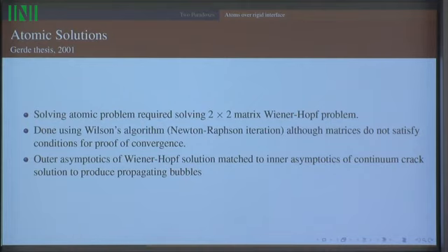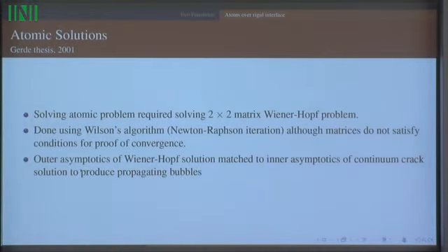So a little bit more on the way this had to run. If you believe in the existence of a continuum solution, then you can work out the asymptotics, which in terms of the power law, as you approach the tips. And I showed you that. It's this r to the 1/2 plus i epsilon. So view that as the outer asymptote of a solution. If you solve the Wiener-Hopf problem, then the Wiener-Hopf problem tells you what atoms do, and then you go far away from it, and you get an outer asymptote. And the outer asymptote is a power law, which you then have to match.